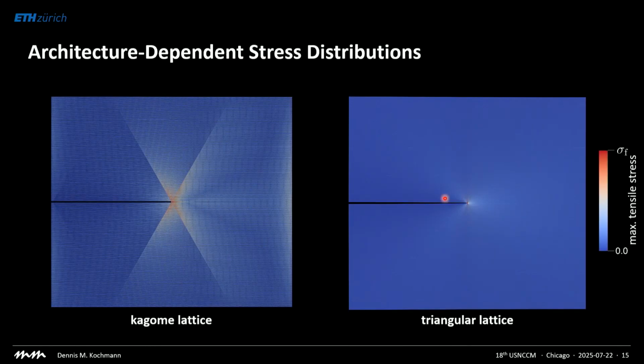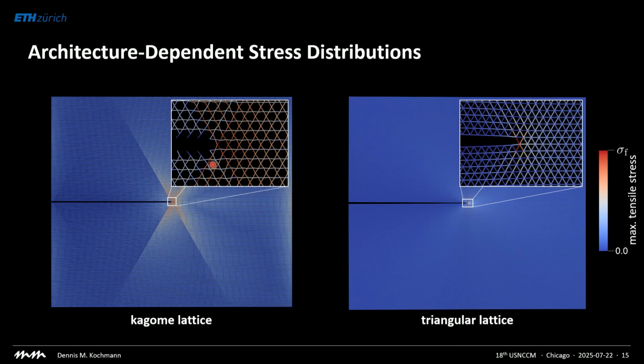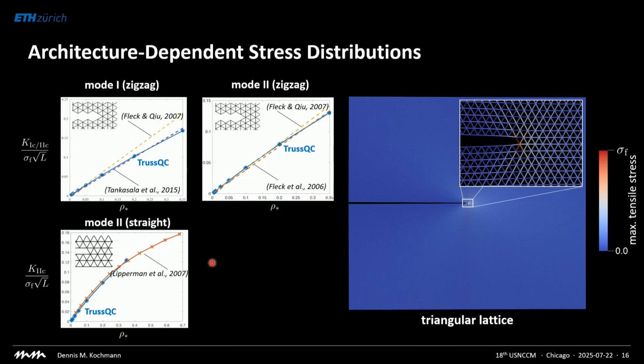Because if you zoom into the discrete solution, you look at the stress distribution, the stresses are distributed very differently based on architecture. And this shows that you can use the architecture and the design also to manufacture structures that have interesting fracture properties. So if you zoom in carefully, load is distributed very differently, and this gives rise to a vastly different fracture toughness of this compared to that, even though they have the same relative density, are easily manufacturable, and so forth. You can also compare this with literature, with experiments, and so forth, and we can see that with just a fraction of the degrees of freedom, we can capture the KIC fracture toughness, KIIC fracture toughness, and you can even see more interesting physics.